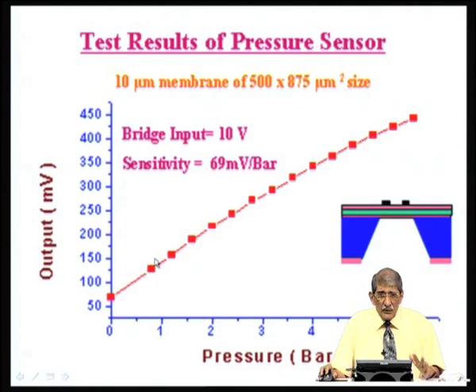If deflection is more, even at lower pressure, the deflection will become comparable to the thickness. Thickness is 10 micron. So, by the time you apply 3 bar pressure, the deflection will be about 1 micron. So, beyond that point, you get the non-linearity. The output is not linear. It has not gone to burst. It can be operated even up to 6 bar, but linearity will not be there.